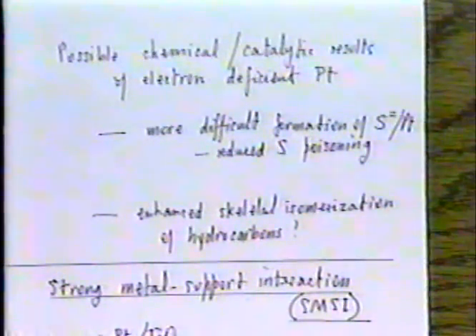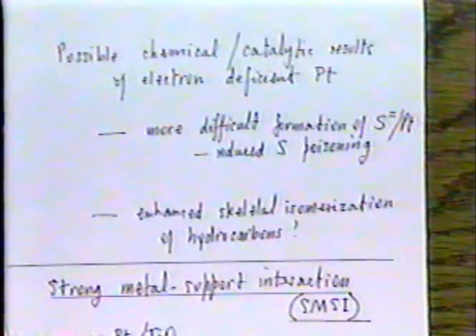Electron deficient platinum was discussed, it must be 10 or 12 years ago now, in relation to the formation of adsorbed anionic species such as sulfur 2-. And in general it was found that when you worked with systems in which the platinum particles had an enhanced electron affinity, that is, the work of electron removal increased along the lines of that diagram we saw at the foot of the previous page, when you had very small platinum particles in a suitable support such that the energy of electron removal from the platinum increased, it was more difficult to form adsorbed sulfur, which resulted in a reduction in the extent of sulfur poisoning for hydrocarbon reactions.